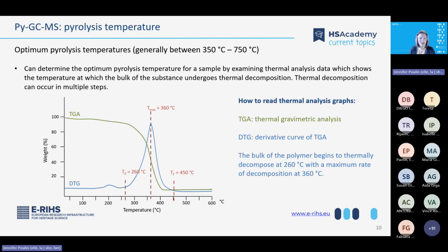The green graph line is, excuse me, the thermal analysis graph. And if we take the first derivative of that graph, you get one that's a little bit easier to read. This is the derivative curve of the TGA. And on this curve, we can see that we start to get some decomposition occurring at about 260 degrees Celsius. The bulk of this imaginary substance is decomposing at 360 degrees Celsius, and it's pretty much completed its decomposition at 450 degrees Celsius.